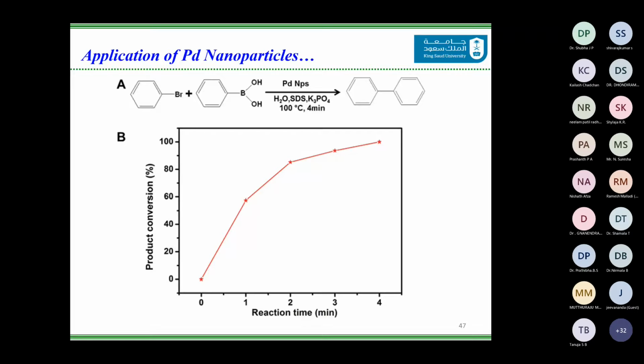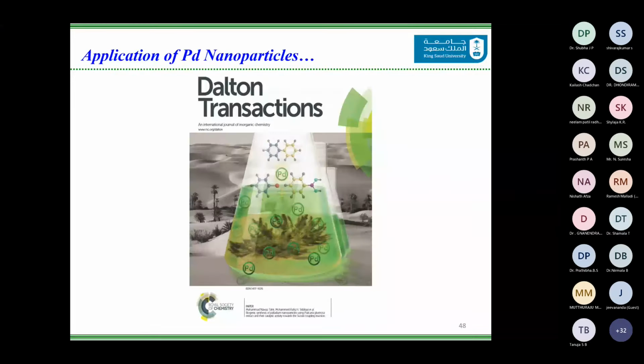However, we use these nanoparticles for Suzuki coupling, where we use bromobenzene and couple it with boronic acid, phenylboronic acid. To our astonishment, we got the Suzuki coupling product within 4 minutes. At 100 degrees centigrade, we got 100% conversion of the reactants to the product. This work was published in Dalton Transactions, and we were again invited to give a cover image for this work. This is what we provided them with.